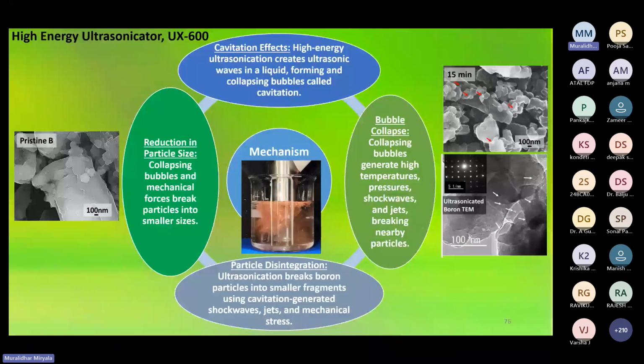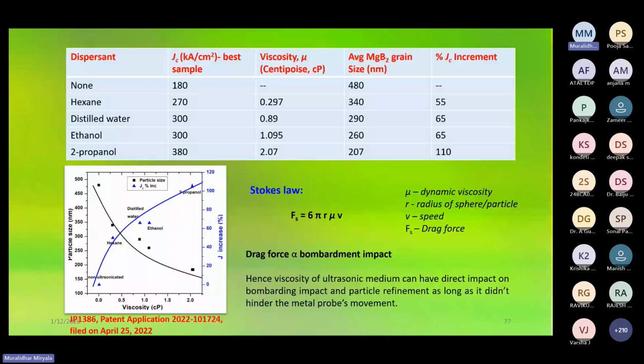Then during this process, what we found is that when you utilize high viscosity ultrasonification media, directly the bombarding effect, like a drag force, is proportional to the bombarding impact.